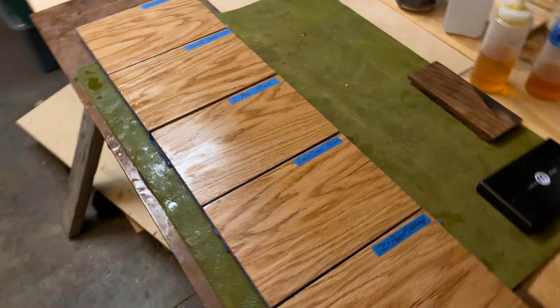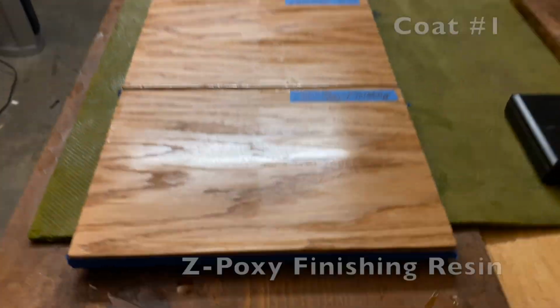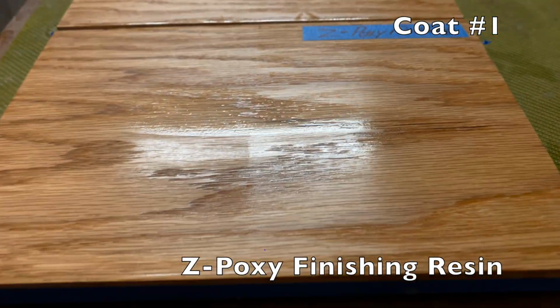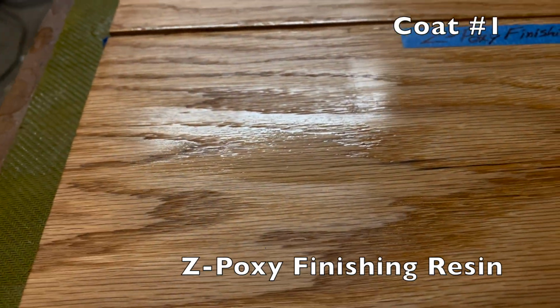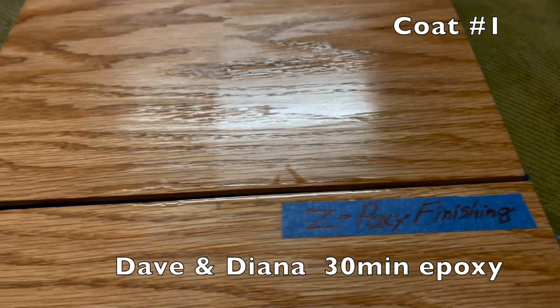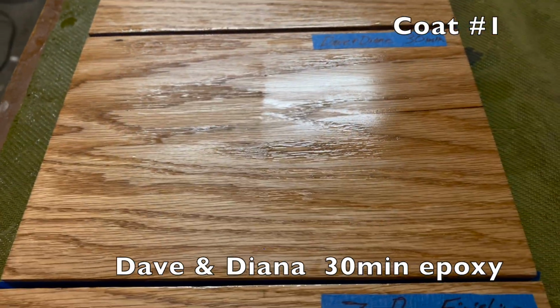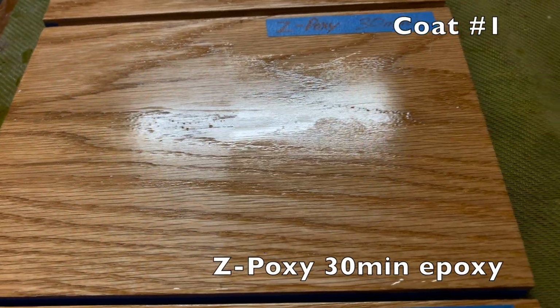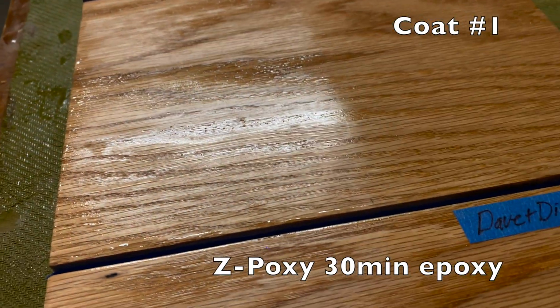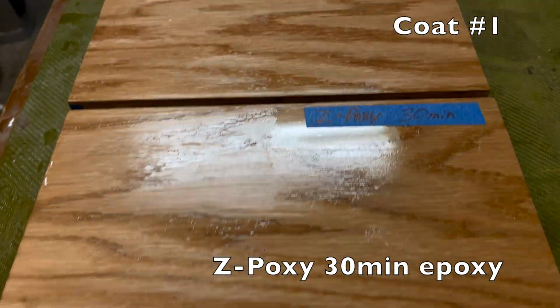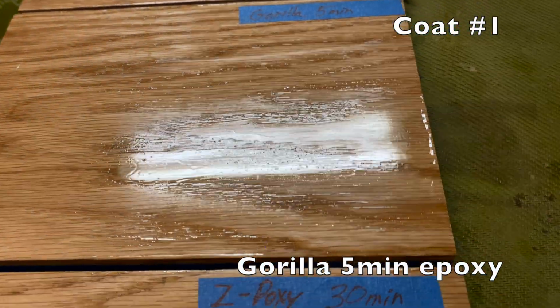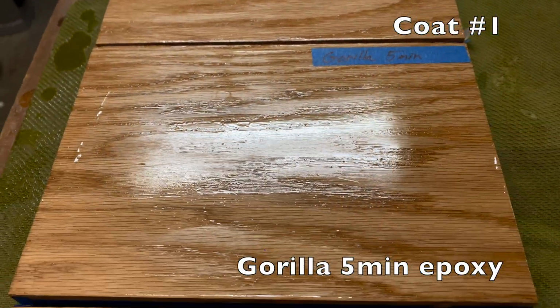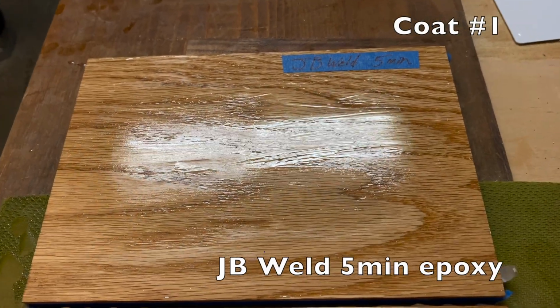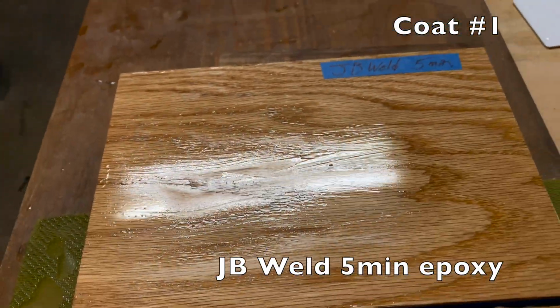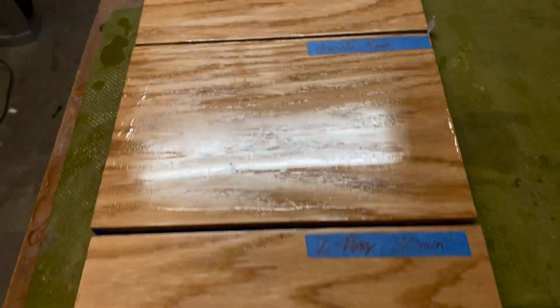And here are the results after the epoxy dried for 24 hours. Remember that the right side of these boards were sealed with shellac, and you can see that the epoxy seems to be standing on the surface more on the right, and that it was absorbed more into the wood on the left. The right sides are more glossy and reflective. The 5-minute epoxies went on so thick that it almost looks like there's not as much difference between the right and the left, although if you look closely you can tell that there was more absorption on the left unsealed sides.